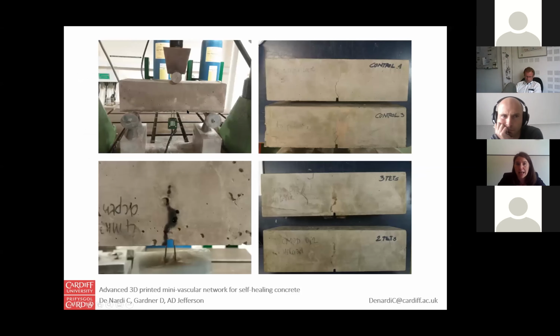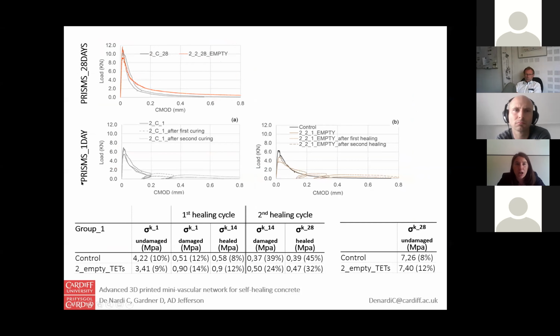Here you can see the samples under the 3-point bend test, which is a classical way to test concrete. Some breakage evidence appears when the TETs are filled with water and just some drops of ink. On the right, you can see the samples already tested, and the discoloration of the concrete is clear evidence of the breakage of the TETs. So here are some results.